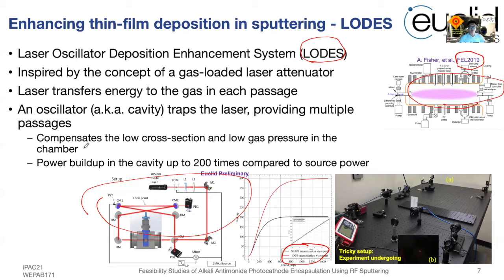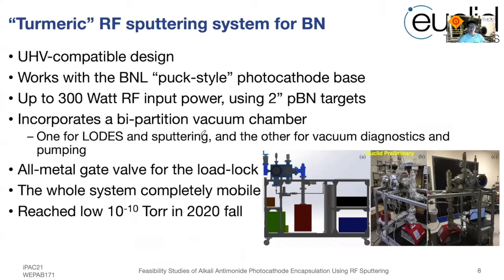Also, since it's a laser cavity, each time the laser traverses the sputtering system, it will deposit energy, and the cavity gives you multiple passages. So this compensates for the low cross-section of the laser and molecule interaction, and also the low gas pressure in the chamber. Taking that into account, we have developed a dedicated sputtering system called Turmeric for boron nitride sputtering.